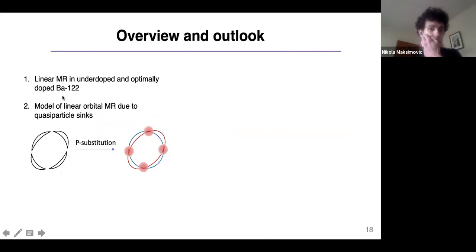So that's the end of my talk. I've presented linear magnetoresistance in underdoped and optimally doped barium-122. And then we have an orbital model for this behavior, which is based on these quasi-particle sinks. In underdoped barium-122, these are regions of large curvature, which slowly evolve into hotspots.